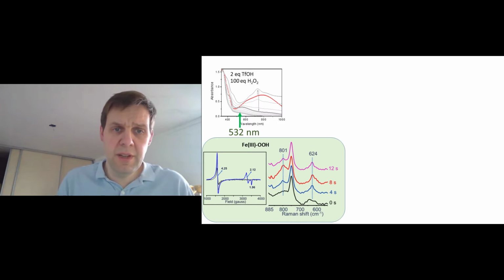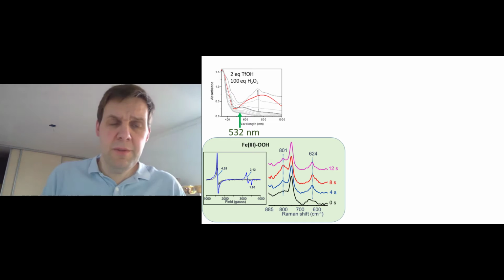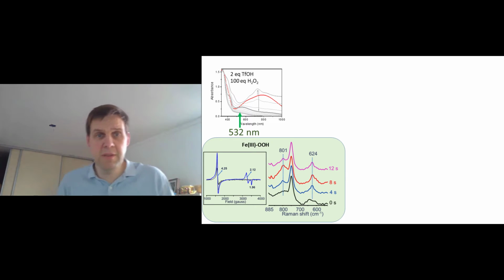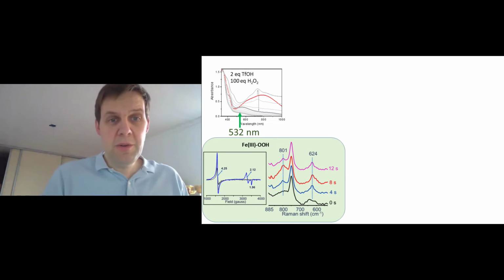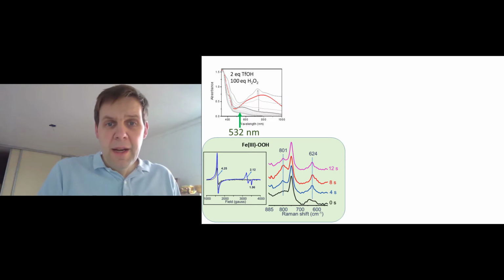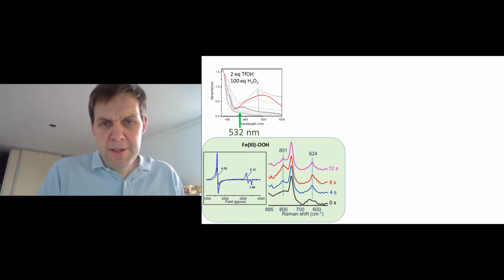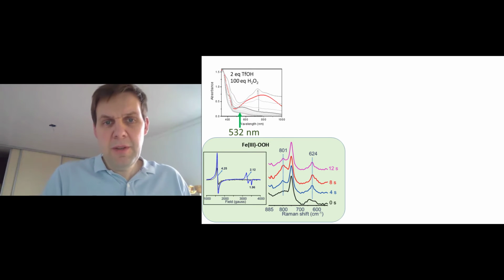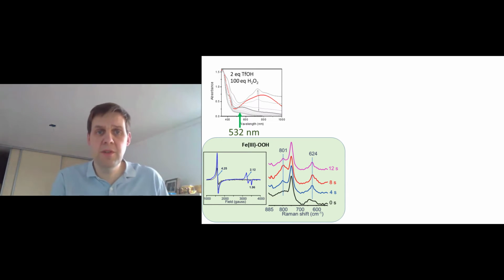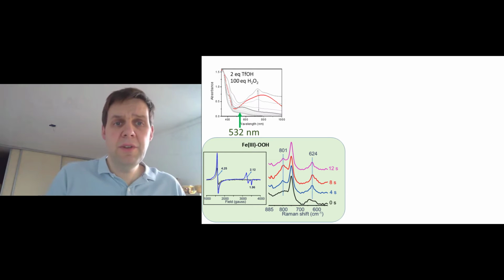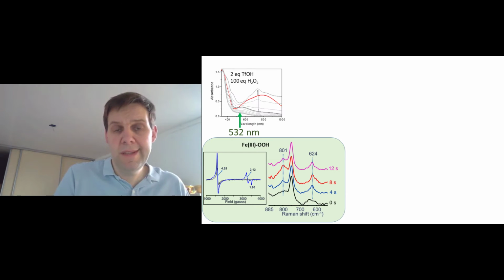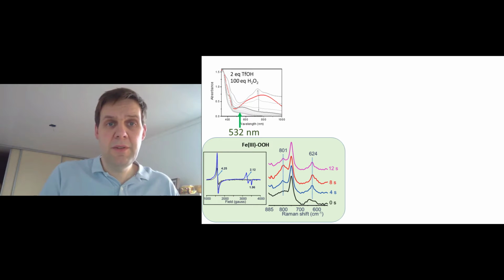So this signal at around 2.12 is typical for a low spin iron 3 peroxy. We have a lot of high spin iron 3 as well, but we happily ignore the huge signal and look at the small signal. And if we look at the Raman spectrum, it's difficult to believe, but it is very reproducible, and we can use labeling to establish the bands are what we think they are. We actually see the bands which are very characteristic of an iron 3 hydroperoxy. So we know that after about 4 or 5 seconds, the predominant species in solution, or one of the species in solution, is an iron 3 hydroperoxy, and thereafter it goes to an iron 3 dimer, which is essentially inert or inactive from a spectroscopic point of view.